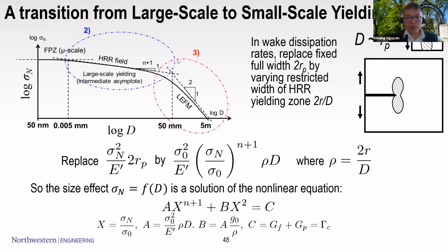So now we have the large-size asymptote, in which the entire structural size covers the entire yielding zone. So we have to replace such an R_p, or constancy of the yielding zone, by a zone that also changes with D. And the way that it changes with D comes from the HRR field solution. And hence we have the transition formulation here, which we can cover in the entire domain of D.